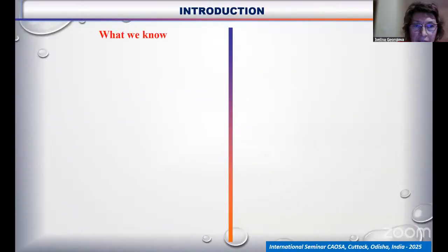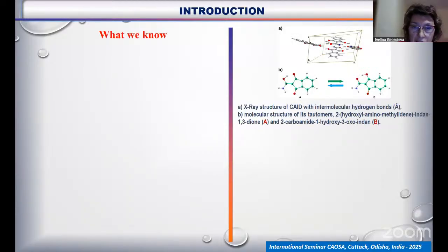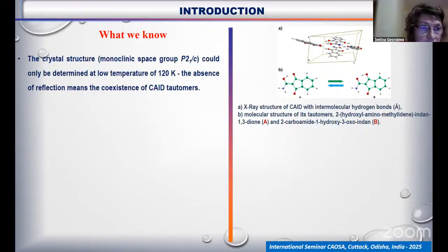So first, what do we know about this structure? This is a molecule whose structure is known. It belongs to a monoclinic space group and consists of 4 molecules which are hydrogen bonded through the donor and acceptor groups. However, this structure could only be determined at a low temperature of 120 Kelvin, and this means that the absence of reflections is information about the coexistence of tautomers. Why is it not possible to determine it at other temperatures?